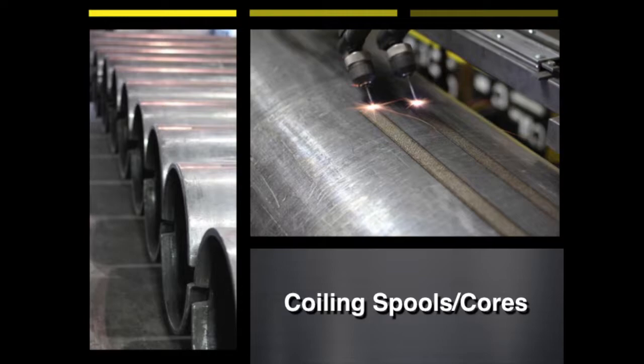We initially did 6 spools with 6 different patterns of coating. All the patterns seemed to work okay, so we settled on a pattern which would be the most cost-effective to apply. In 2011, we coated over 1,100 of these spools for one particular customer. According to the cold mill engineer at this plant, this modification bought them approximately 30 minutes of mill productivity per day.